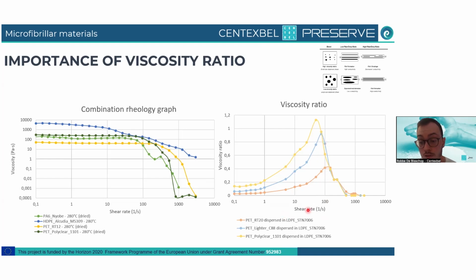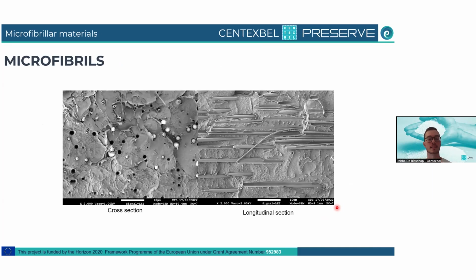Again, this will differ with the shear rate. So depending on your extrusion process, this will be different, but also just by using a different grade, you can have a very large viscosity ratio. So we look at these different ones to see how we create these fibrils.